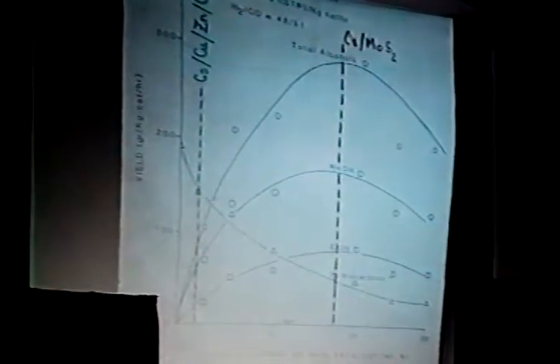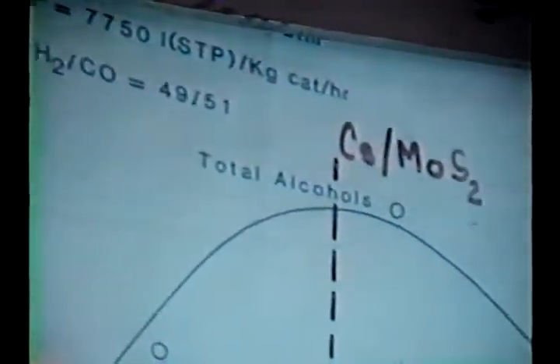Now, when we started, we already had work in progress on the copper catalyst, where we studied the whole series of the light alkalis and heavy alkalis, and we determined on those copper catalysts that cesium is much better for you than the lithium or sodium. And so we really, instead of reproducing, which we initially did, the Dow chemistry, which was done with potassium, we started with cesium. And here is the catalytic pattern of the synthesis, depending on cesium loading.